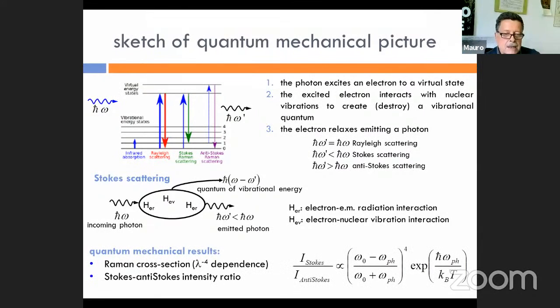There are two perturbations. Two first order perturbations make a second order process. Using a quantum mechanical description of the Raman effect, full calculation of the Raman cross-section, that is the probability of the event, can be calculated. And using these tools, we can recover very interesting results, such as the intensity ratio of the Stokes to anti-Stokes lines, and the dependence of the Raman cross-section on the excitation wavelength to the -4th exponent.